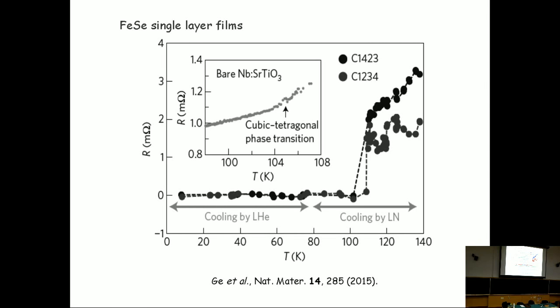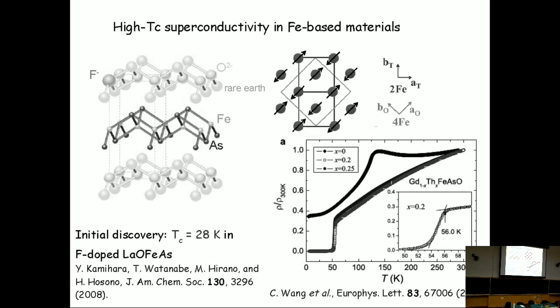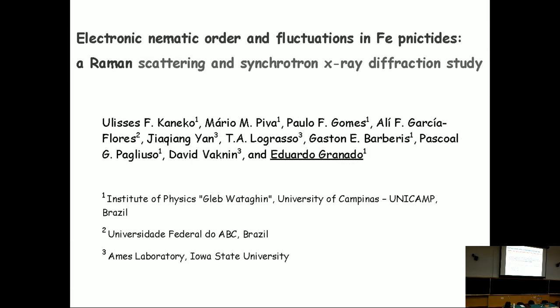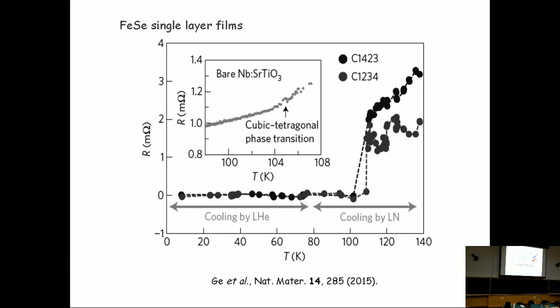That is not the only system where superconductivity has been found in the iron materials. For instance, the iron selenium, which only has this tetrahedral network with iron, but instead of arsenic you have selenium, and no intervening planes of other elements. You just have a stacking of iron selenium, and in the iron selenium system there is found superconductivity too, and